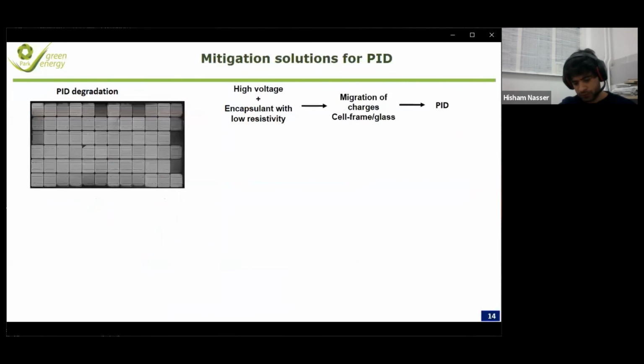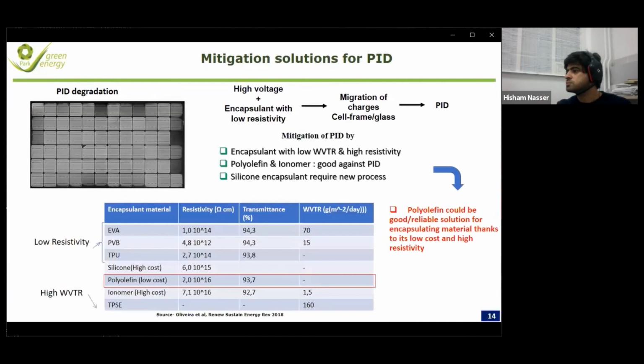So, for the PID, the encapsulating layer of the cell must provide perfect electrical insulation in order to mitigate this problem. As you know, in the PV market, EVA remains the most dominant due to its low cost. So there are certain polymers which can be considered as alternatives, for example PVB, TPU, silicone, polyolefin, and ionomer. An encapsulant with a low water vapor transmission rate and high resistivity is the most important solution.